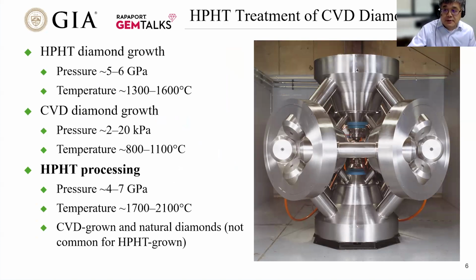I will talk very briefly about HPHT treatment of CVD diamond. For commercial growth, it's a balance of quantity and speed. Many CVD diamonds are produced at a reasonably fast speed, but the CVD diamonds could have a decent amount of brown color. It is necessary to remove the brown color by HPHT treatment. A few conditions are summarized here. As we pointed out previously, HPHT directly grows diamond at high pressure and high temperature. The pressure is about 5 to 6 GPa, and the temperature is 1300 to 1600 degrees C.